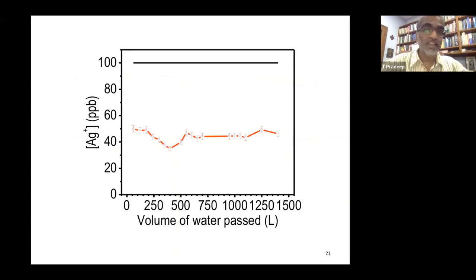Now, this has been very well studied for a long time. Silver releases silver ions in water, and that is an antimicrobial agent at very low concentrations. But then silver nanoparticles don't release silver ions in real water situations after some time. That is because nanoparticle surfaces are highly active. They deposit calcium silicate on the surface. As soon as a tiny layer of calcium silicate comes on the surface, the amount of silver release is less and there is no antibacterial action.